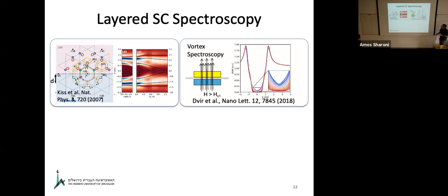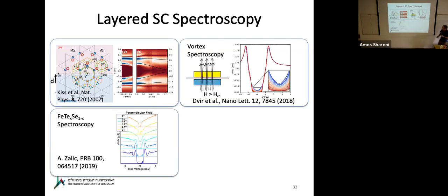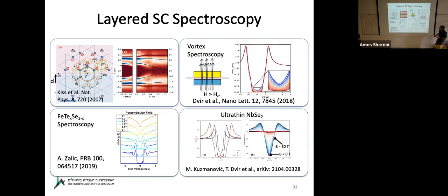The second thing we did was carry out spectroscopy in the presence of superconducting vortices and measure the density of states of vortices. This is another paper by Tom Dvir. We could, with a lot of effort, measure the topological superconductor iron telluride selenide and see that its gap survives even if you apply a very high field, probably because of sparsity of the vortex states. And we could measure this niobium diselenide at a high in-plane magnetic field. Niobium diselenide survives high in-plane magnetic field, and because of what I'm going to say later, it's important to understand